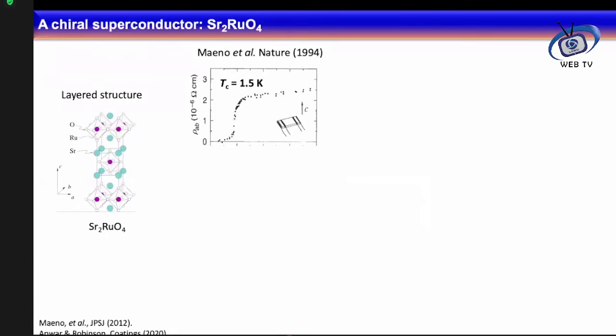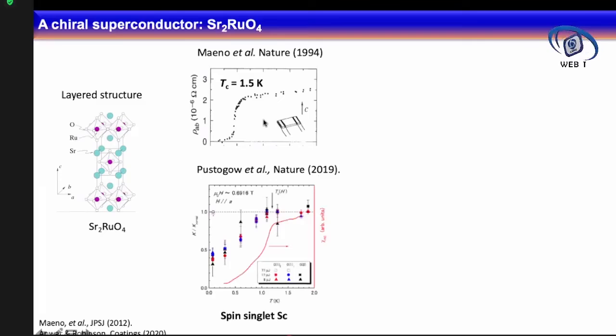There is a superconductor which is very important and very interesting since 1994. This is strontium-2 ruthenium-4. It is a layered superconductor, meaning that its structure is a layered structure like this here. And in 1994, Professor Maeno from Japan discovered superconductivity in this material below 1.5 Kelvin. And since then, a lot of work has already been done on this material to understand its superconductivity.